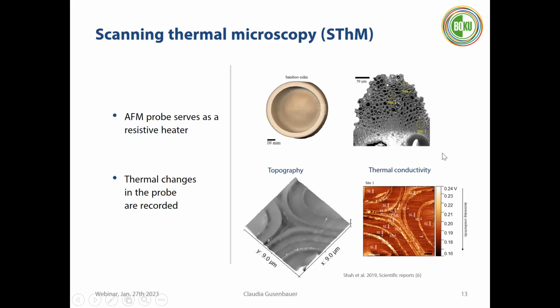And by also following the temperature changes within our samples, we could see different thermal conductivity in the cross-section of bamboo cell walls. What is happening is the tip is set to a certain temperature and is scanning the sample, and certain areas are able to conduct the heat of the tip, and some areas have lower capability of transferring the heat. And we can capture that. For example, here you can see the different cell wall layers of the bamboo cell wall. And we see that certain cell wall layers have good conductivity, and some cell wall layers have worse conductivity.